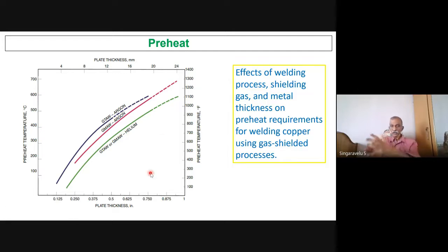And coming to the most important one, the preheat for copper, right? This is a very good diagram. Please try to understand this. The welding process, the shielding gas, and the metal thickness decide the preheat requirement. Base metal thickness: in the case of steel welding, when thickness is higher you preheat, there is a formula, and based upon the composition you can appreciate the carbon equivalent and all. Here, the process and the shielding gas become a vital input to decide the preheat temperature.